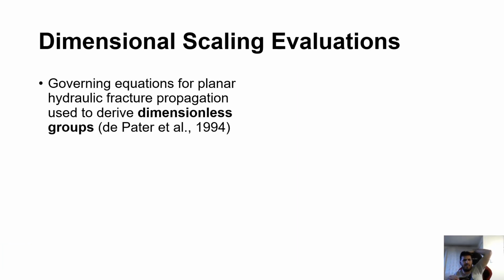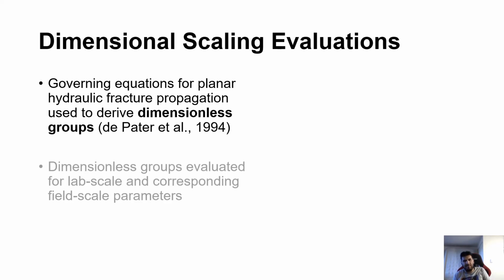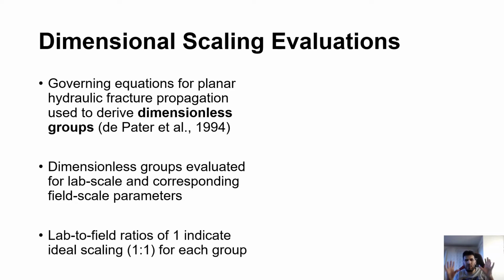Now, moving into the dimensional scaling evaluations, which is the primary topic of this paper, I borrowed de Pater's analysis from 1994, where he took the governing equations for planar simple hydraulic fracture propagation and derived a set of dimensionless groups that could be used for scaling analysis. These dimensionless groups can be evaluated for lab scale conditions and the corresponding field scale conditions, and then we can see how well those two numbers are close to each other.